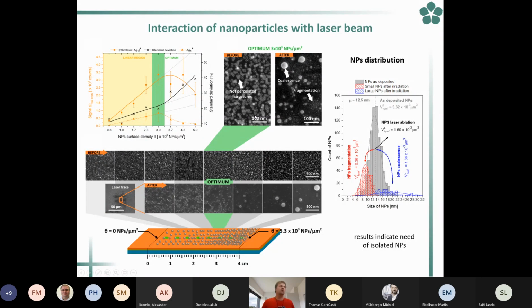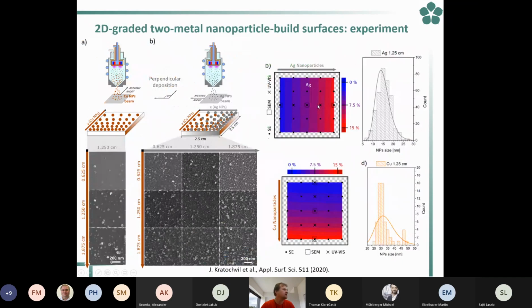If the nanoparticles are closer, they tend to coagulate. They have the energy and they try to coagulate together, encouraged to make some friendship with the neighbors. While if there are some bigger nanoparticles with a lower surface density, they simply are not able to absorb all this energy, and they explode. So then we observe the fragmentation towards some smaller